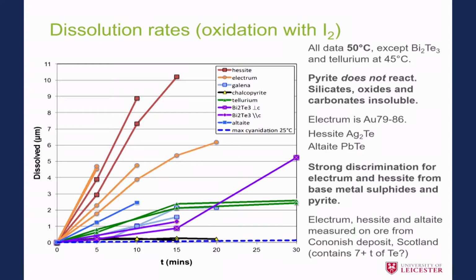Cononish, then that contains a considerable amount of tellurium as hessite, and we'd like to be able to recover that too. So we should be able to leach out both the gold and the silver and the tellurium and recover those.